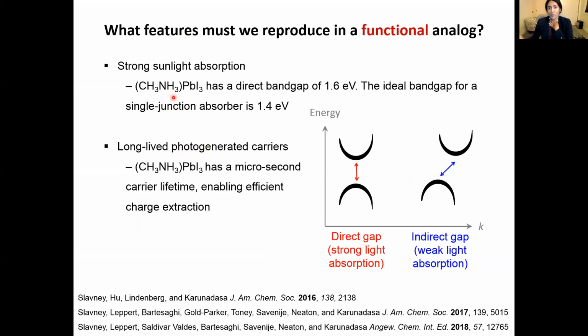So why is the lead iodide perovskite so great? Because it has a direct band gap of 1.6, which is pretty close to 1.4. So a direct band gap material is shown here, and a direct band gap material absorbs sunlight very efficiently. Some materials have an indirect band gap, and those materials are less efficient at absorbing sunlight. So it absorbs sunlight very weakly, which is not a deal breaker. It just means that you need more of that material. So with a direct band gap material, you need a thin layer of an absorber. With an indirect band gap material like silicon, you need a thick layer of the material.